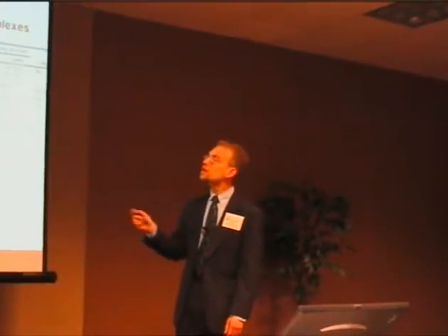So one example is a titanium-modified material where cyclohexene has been oxidized. There's a number of other substrates that have been tested for the oxidation. Also glycine, and let's see, there are other enzymes represented in this table, horseradish peroxidase, have been introduced. The advantage of using these materials for enzymes is that it stabilizes them, both thermally and to the chemical environment of the liquid that surrounds the particles, over what they would experience on their own.